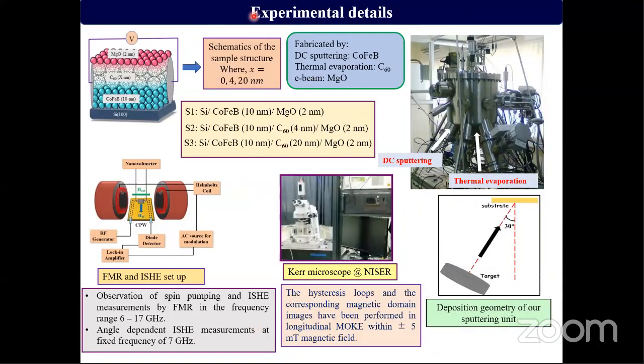So this is the experimental detail. We have prepared 3 samples. On top of a silicon substrate, we have prepared a single layer of cobalt iron boron, 10 nanometer, deposited using DC sputtering. Then we have deposited C60 of 4 nanometer and 20 nanometer. This is the sputtering unit of our lab, and we have performed the FMR and ISHE measurements.